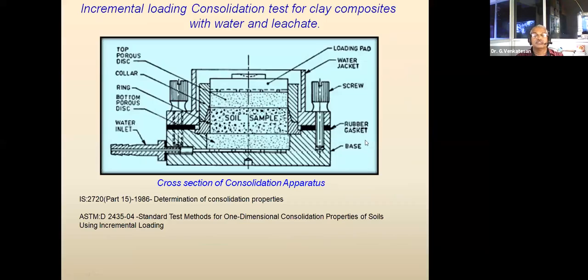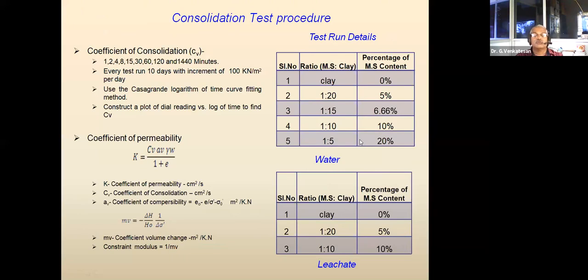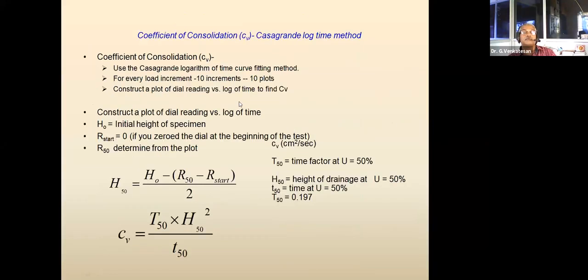It is an incremental loading consolidation test apparatus in our laboratory. So a trial run is taken from the consolidation test. We know that for clay soil, to find the permeability, the falling head permeability test is used, but for accuracy we took it from the consolidation test using the formula K equals Cv av gamma w, 1 plus e. We found the K value indirectly by calculating the Cv value. Each test run is taken for each ratio of microsilica clay. We took two pore liquids, one water and the next leachate. The 5 ratios with water were taken, and 3 ratios with leachate were taken during the various consolidation tests. We did it to find the K value indirectly.